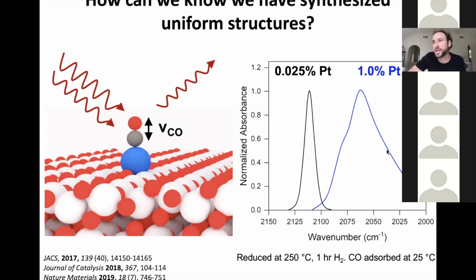The broad stretch tells you that CO is likely sitting in lots of different coordination environments on a surface, and each one of these coordination environments perturbs the CO molecule a little bit differently, and as a result, its vibrational frequency is a little bit different. Also, what you see is the relative position of these bands. This one falls closer to the gas phase CO stretch, which is here, as compared to this one. And that's likely because the platinum that this is adsorbing to is cationic. It results in less back bonding, or electron donation, into CO, and so CO's bond is not stretched as far as it is when maybe you're on a metallic cluster.